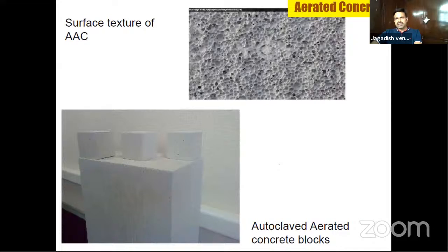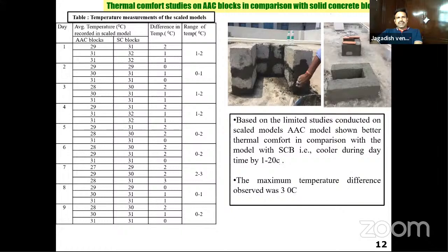You can see the AAC, autoclaved aerated concrete block, is such an example. You can see the surface texture of the AAC block. One of the projects we did with Ultratech Cement, we did some experiments wherein the block density is around 650 kg per cubic meter. And when compared to the solid concrete blocks, you can reduce the temperature. There are like 2 to 3 degrees centigrade less temperature when compared with the solid concrete blocks.